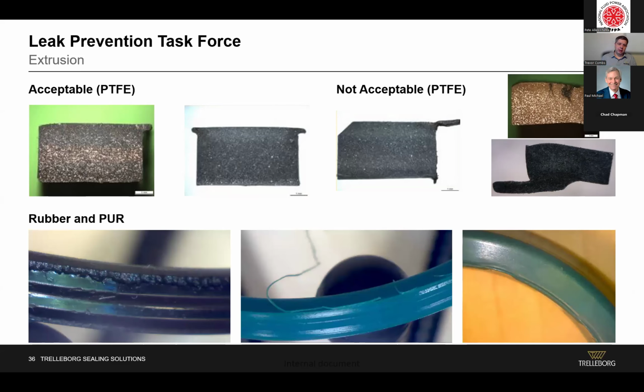For rubber and polyurethane, they're going to look a little bit different. If you're operating the seals outside of their application limits, or if there are excessive clearances, too much pressure, or too high temperature, they can start to extrude. With rubber seals, you'll see little chunks torn off. We call it nibbling, where the pressure is forcing that rubber into the gap and it's getting torn off. Polyurethane seals will tend to shear, coming off in slivers or being pinched or deformed. Those are all signs of extrusion. So you want to look at addressing the design, the pressure, the clearances, and misalignment potentially could be another cause.